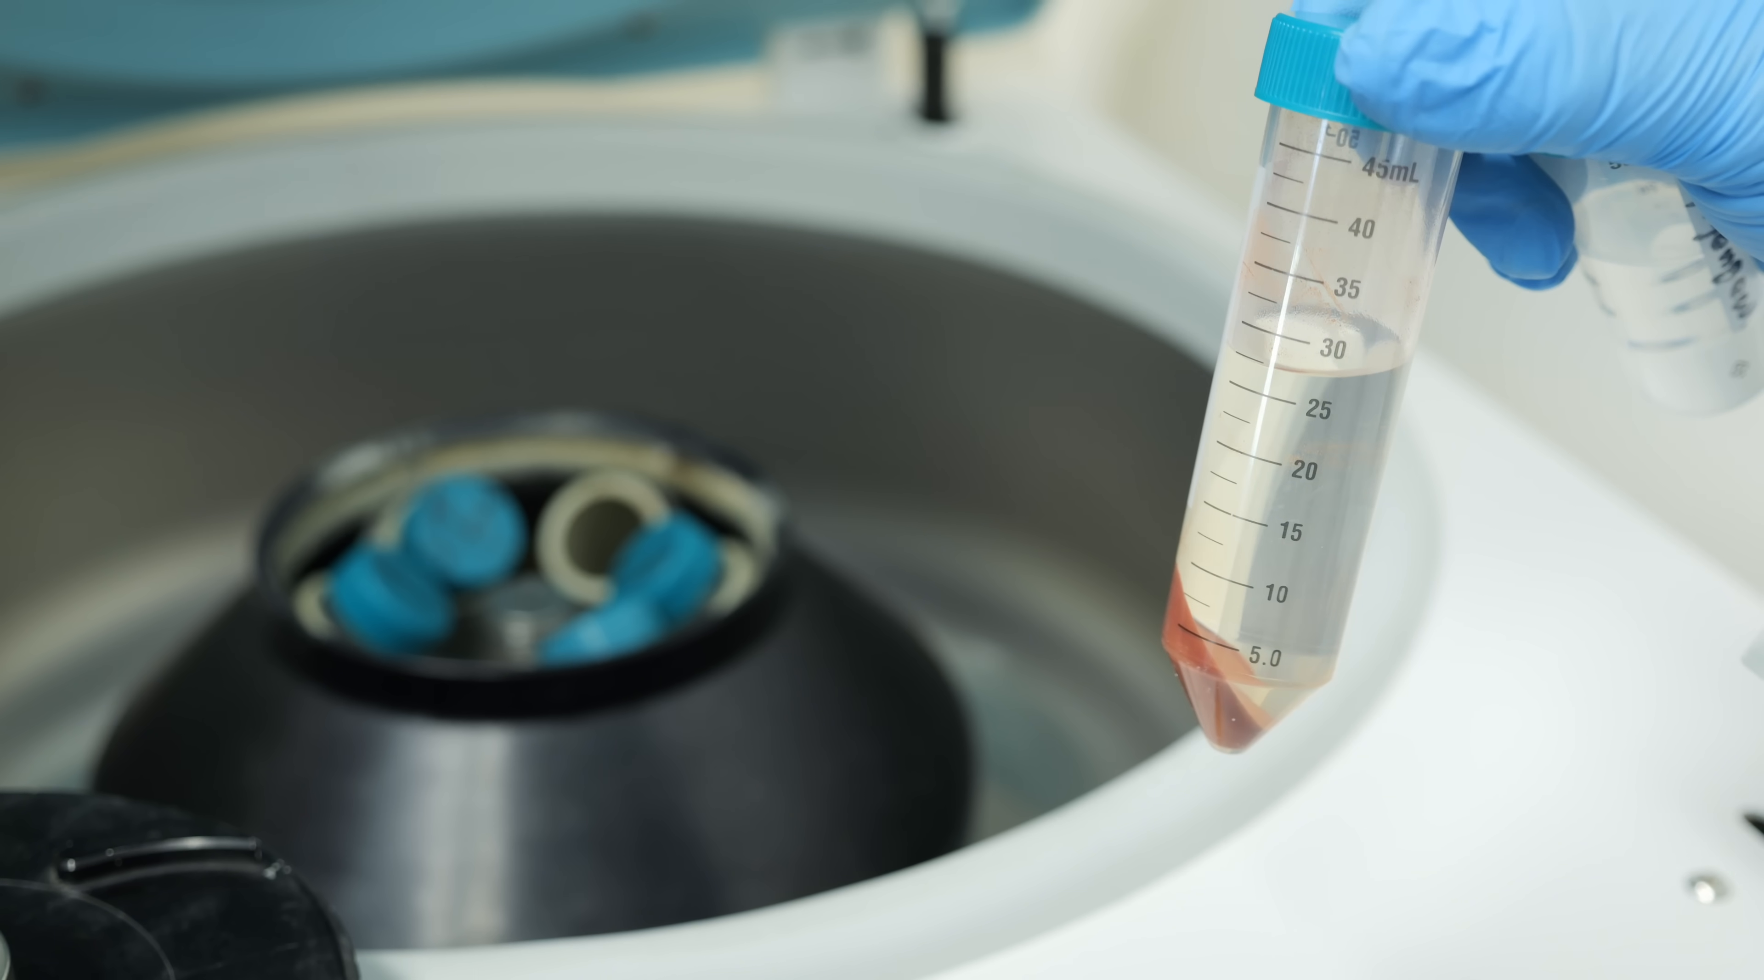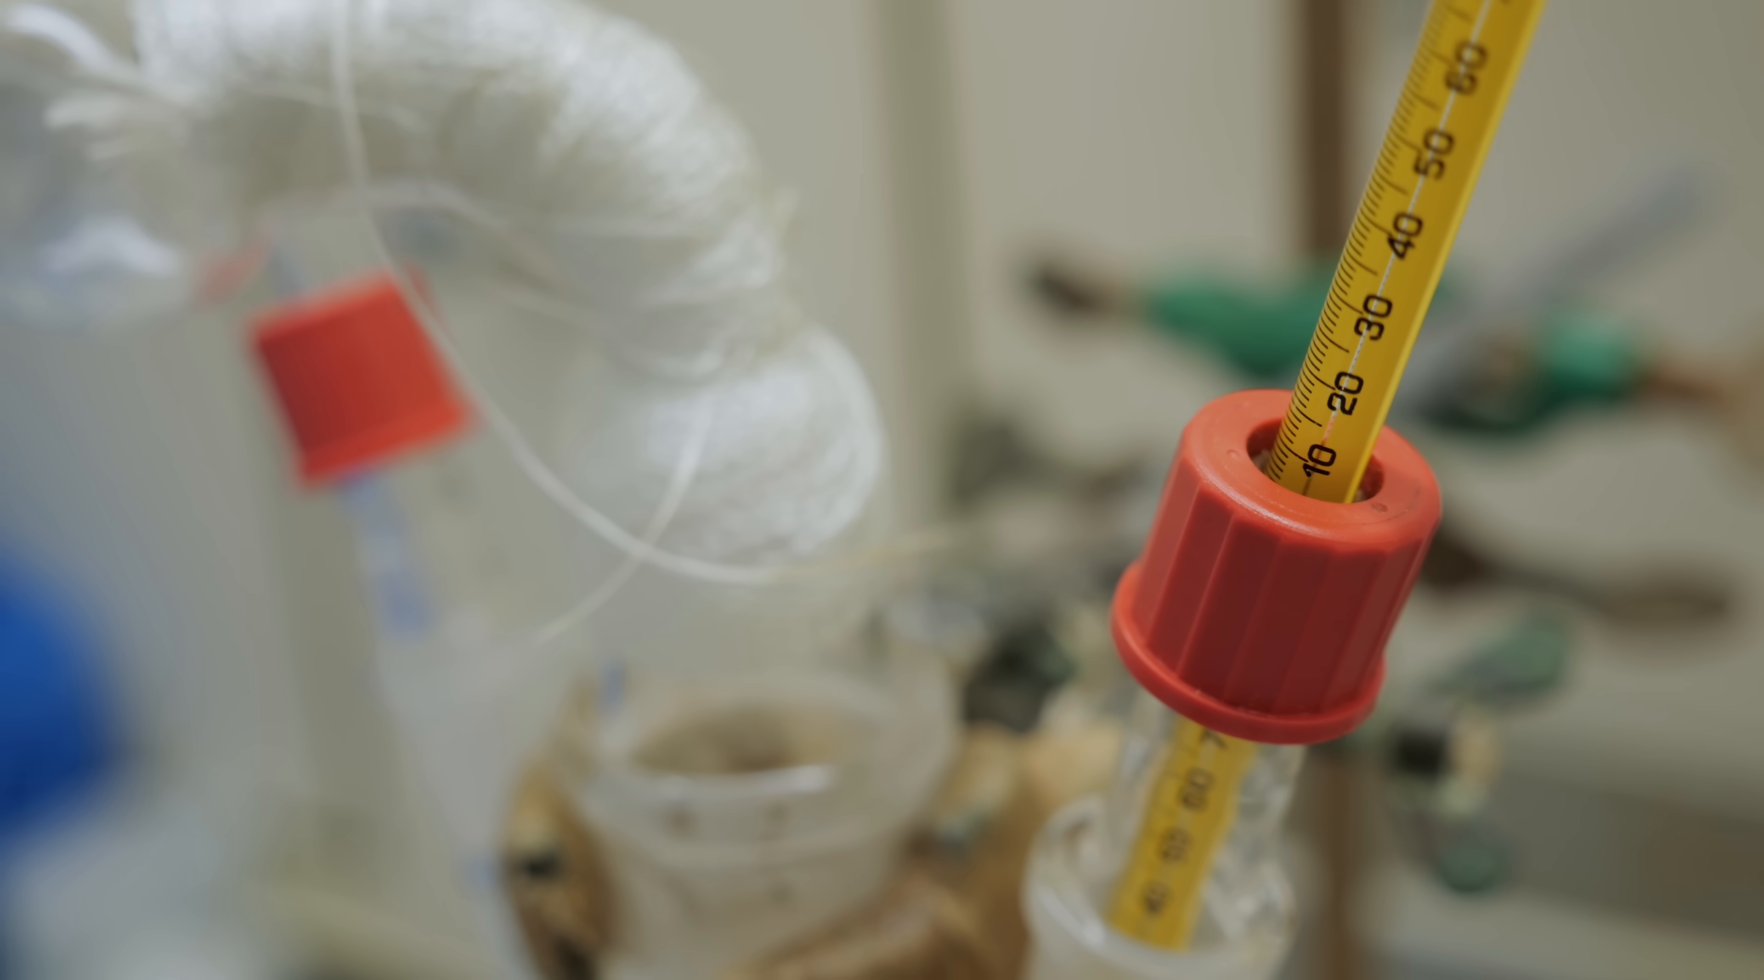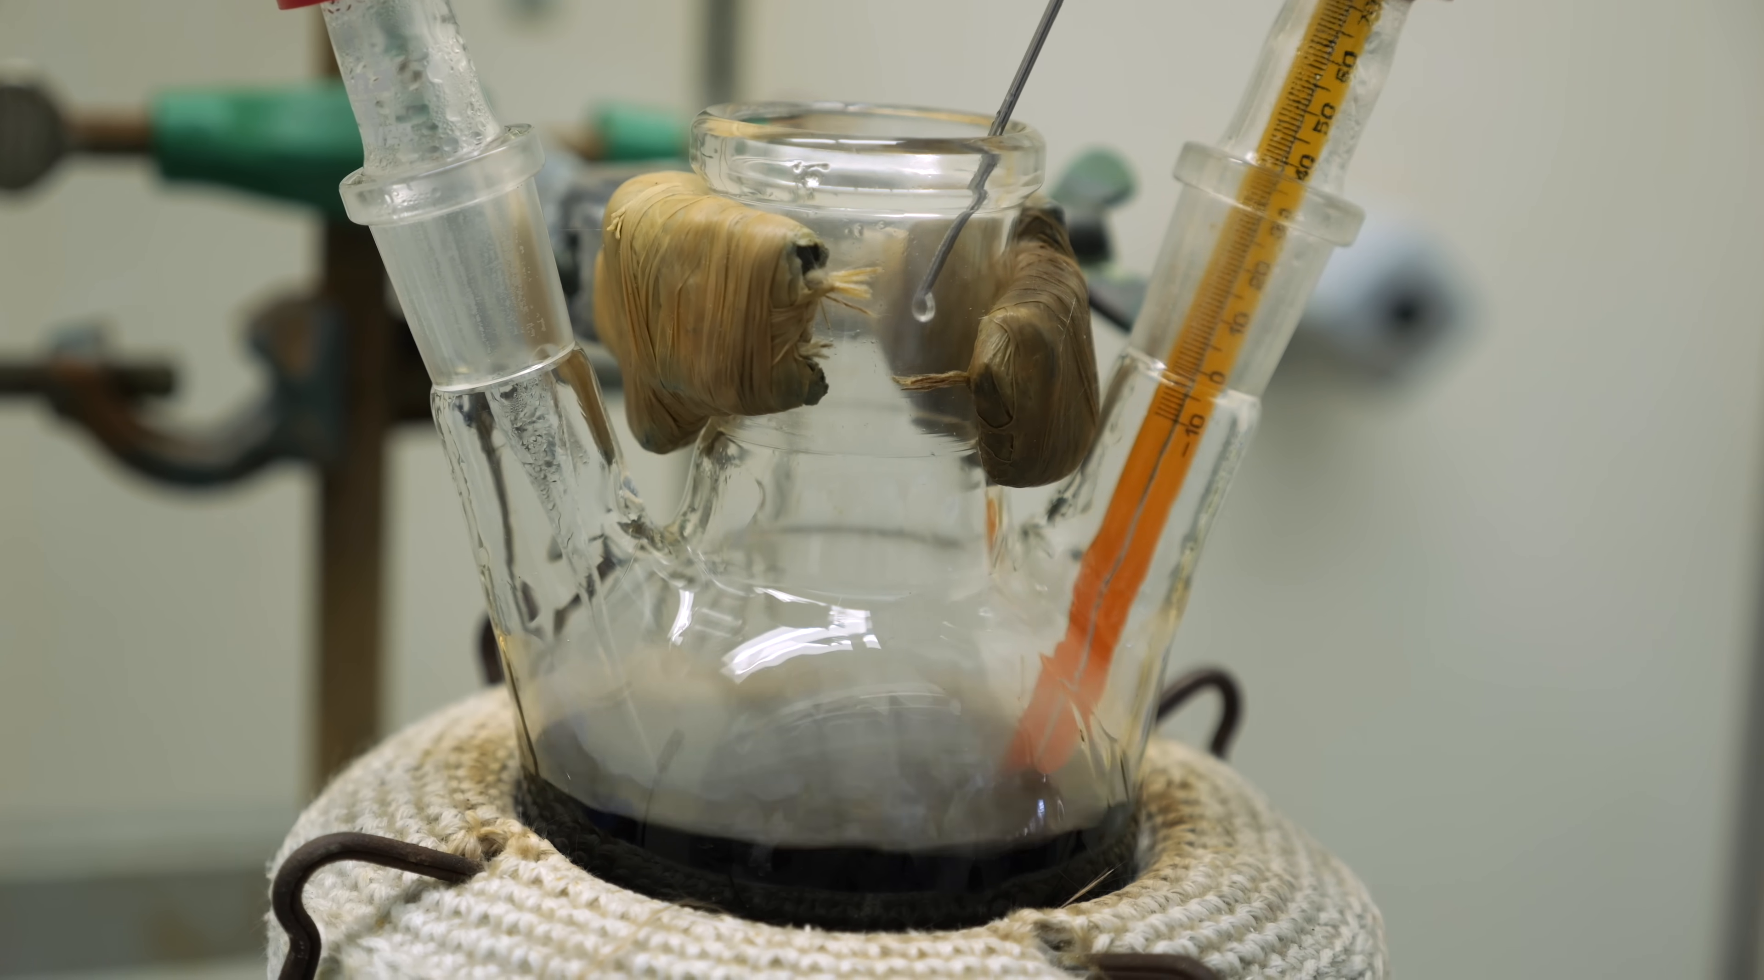We've grown nanocrystals to precisely the right size, down to a few atoms, and we've done all of that in a lab in just a few hours. If you're wondering, the exact size of the crystals that is formed is determined by, for example, the temperature that the reaction happened at, or how long everything was kept at that temperature, and also the various ligands that were added, and so these variables will control what the final colors will be that we'll get.